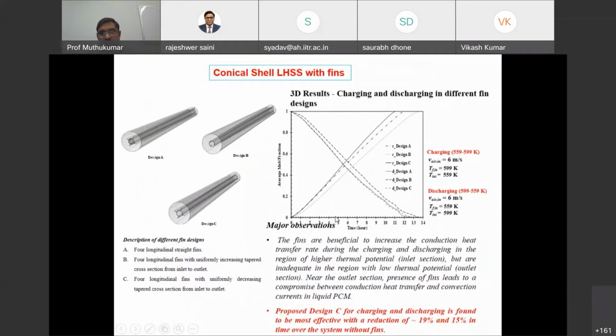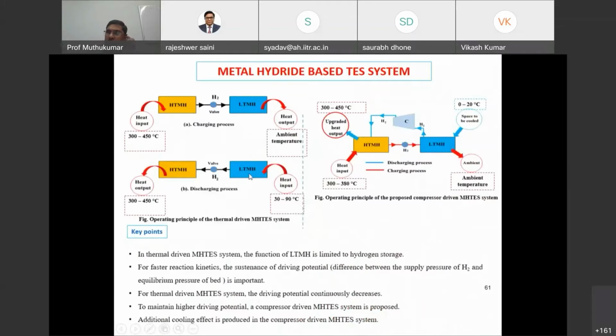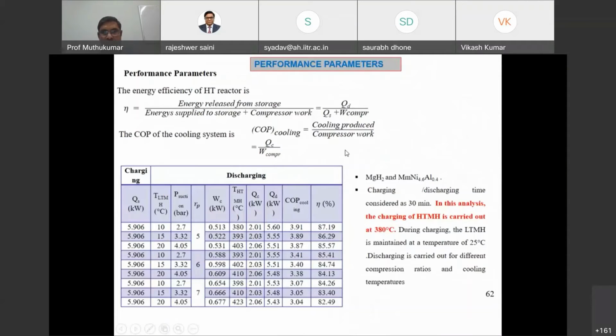This design C was found to reduce the charging and discharging time by about 19% and 15%. Okay, this is what I have discussed, the metal hydride based polygeneration system. This system provides simultaneous thermal storage, thermal upgradation, and cooling. All 3 things are possible using a single system. So far we have done the thermodynamic study, and recently we have initiated the testing of the high temperature thermal storage system using magnesium based hydride. Soon we are going to couple it with the low temperature alloy.